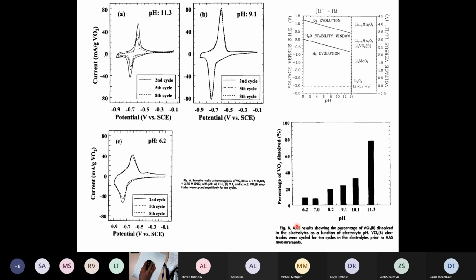So this is what I'm talking about. We did atomic absorption of the electrolytes and then back calculated the percentage of the vanadium oxide that dissolved as a function of the pH. So you can see that this is only 10 cycles, okay, 10 cycles only. So you can see that 10% of the vanadium oxide was dissolved even at almost neutral pH after these 10 cycles. So this was a choice of electrode materials that could demonstrate that you could do this, but not a good choice for a long-lived cell.